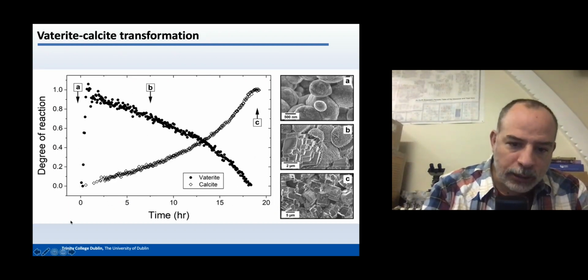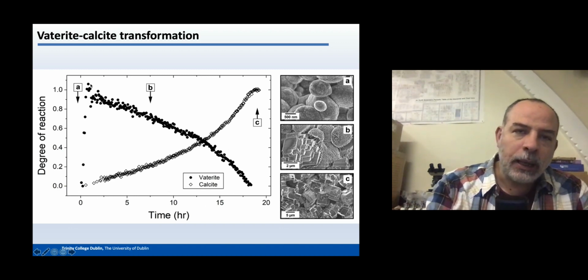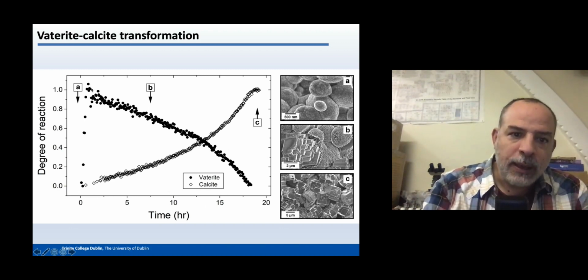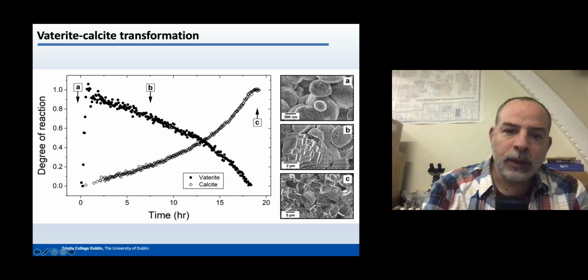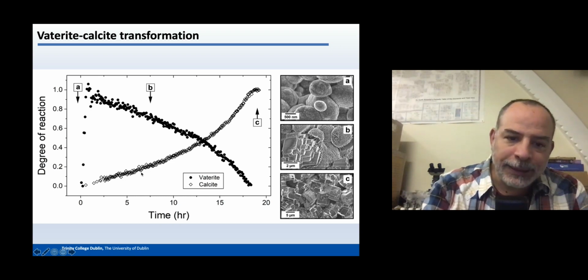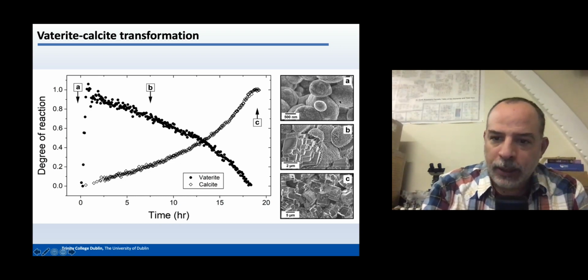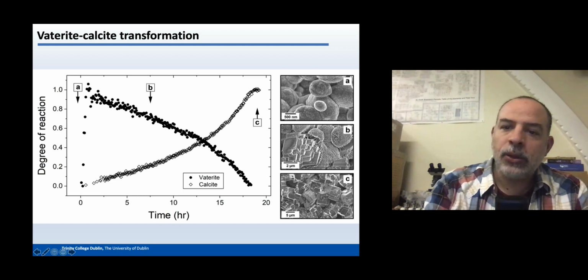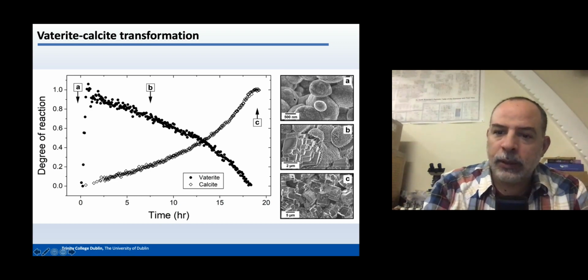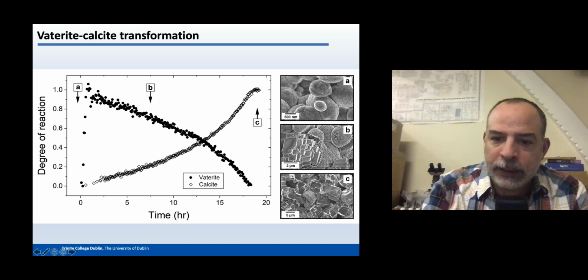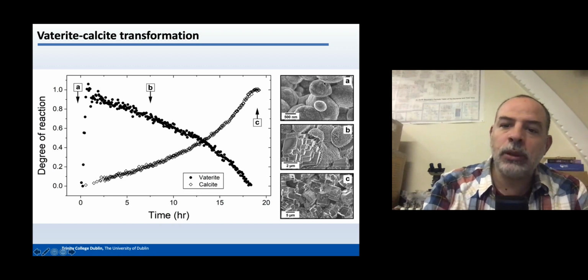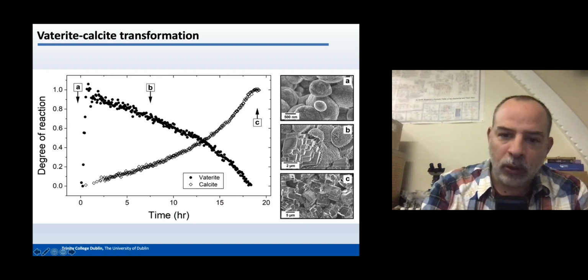But here you see the time is different. This is 20 hours, and this was a very long experiment in which vaterite was slowly decaying, dissolving, and calcite was slowly growing. This is what you see in the pictures. These spherulites of vaterite are slowly dissolving and calcite is forming via dissolution and recrystallization. And at the end, you have finally only calcite.